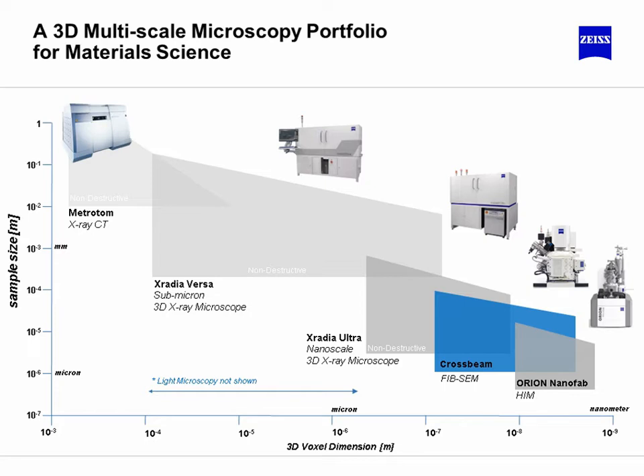Coming back to our 3D multiscale microscopy graph, FIB-SEM tomography covers the application space highlighted in blue. Volumes of interest with sizes from a few microns up to around 100 microns can be analyzed with a resolution down to a few nanometers. FIB-SEM tomography thus fits between X-ray microscopy tomography and other tomography techniques like TEM or atom probe tomography.